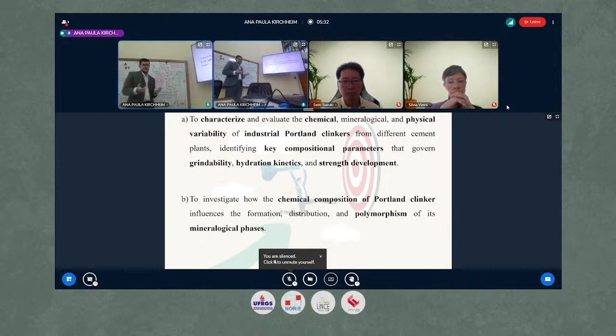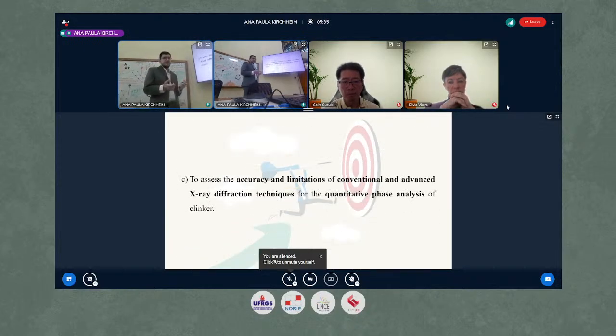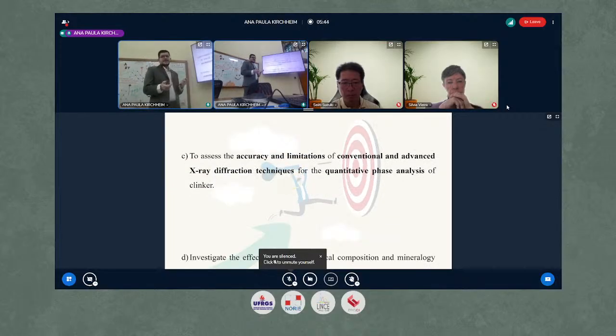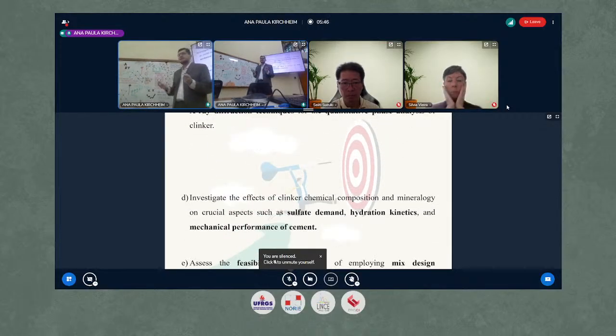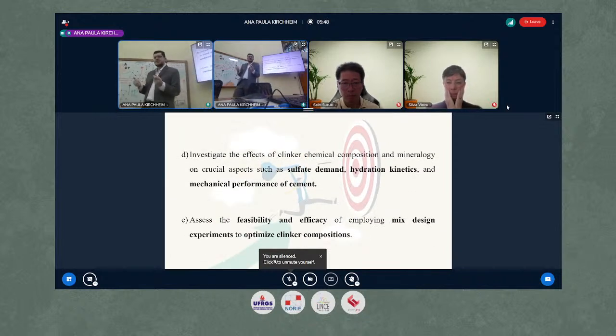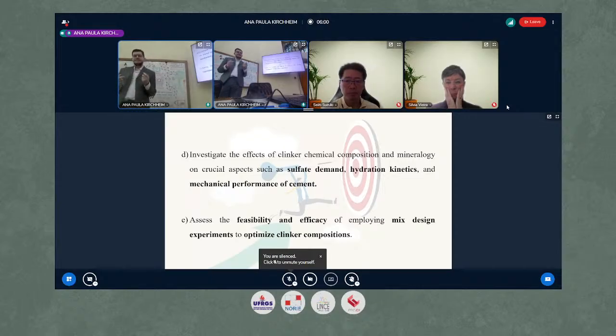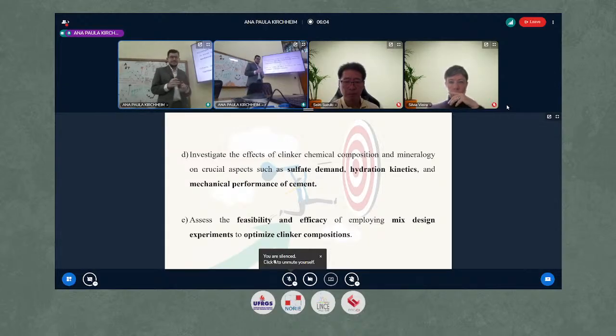We also assessed the accuracy and limitations of conventional and advanced X-ray diffraction techniques for the quantitative phase analysis of clinker, and investigated the effects of clinker chemical composition and mineralogy on crucial aspects such as sulfate demand, hydration kinetics, and mechanical performance of cement. Finally, we assessed the feasibility and efficacy of employing mixture design experiments to optimize clinker compositions.